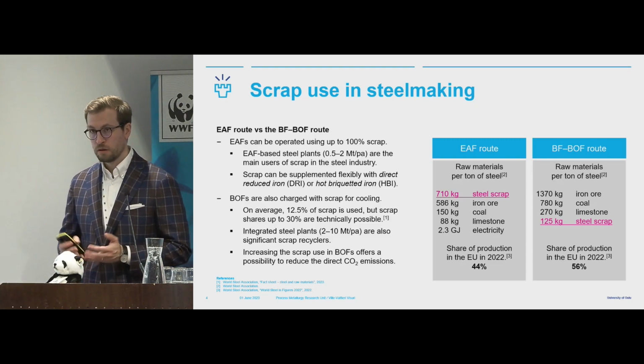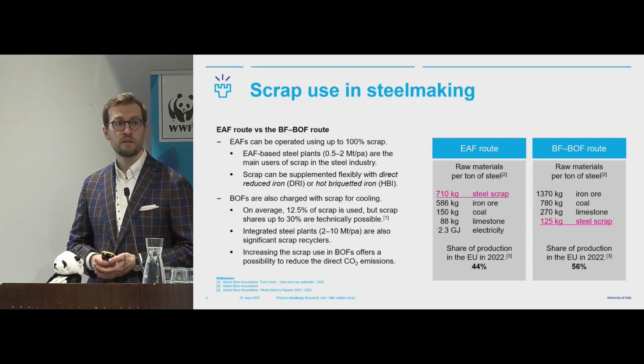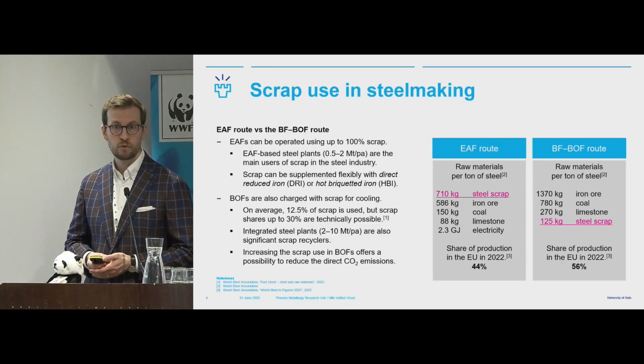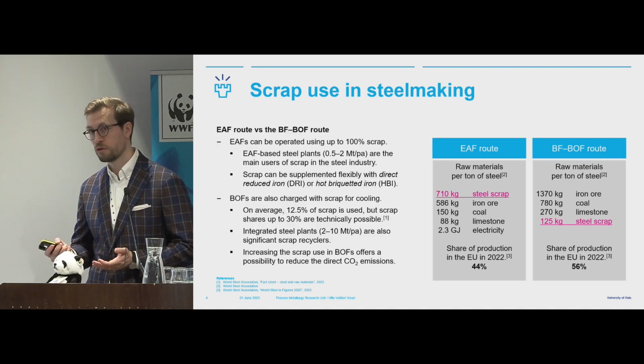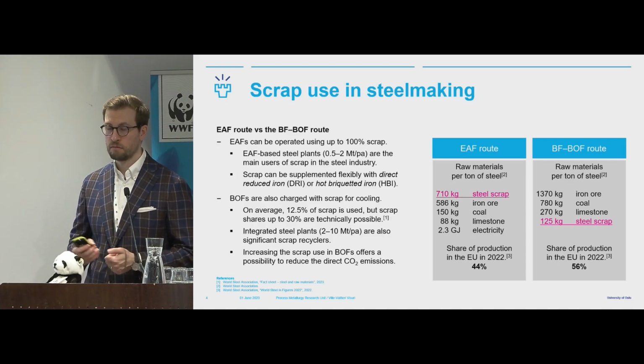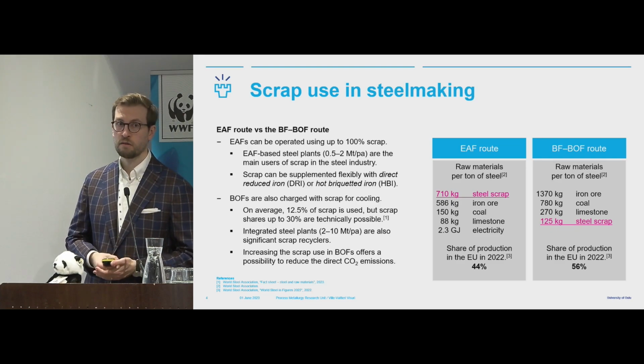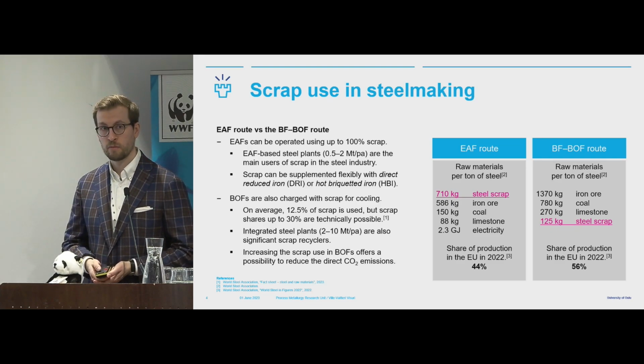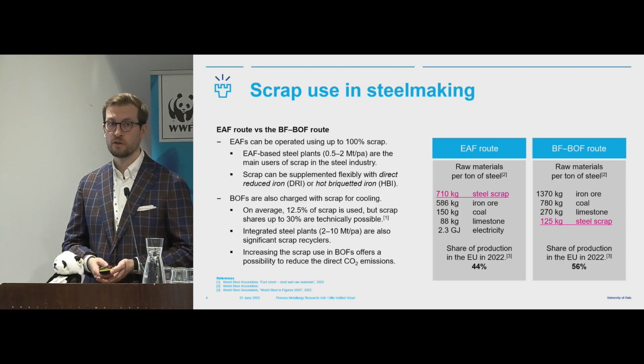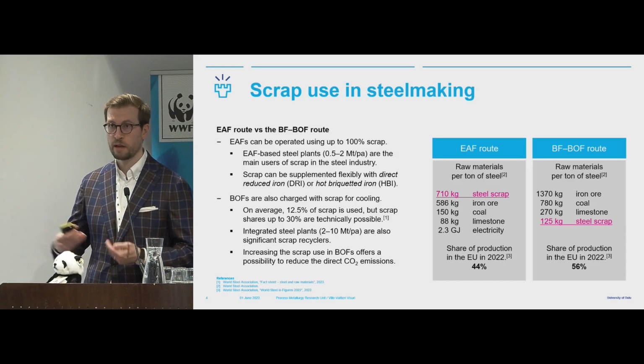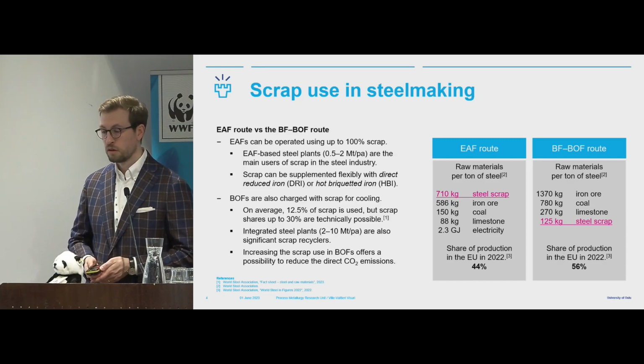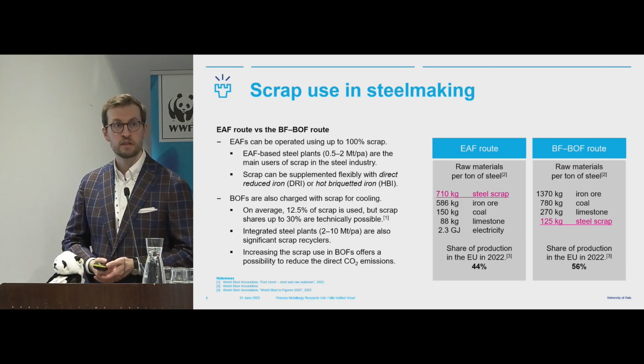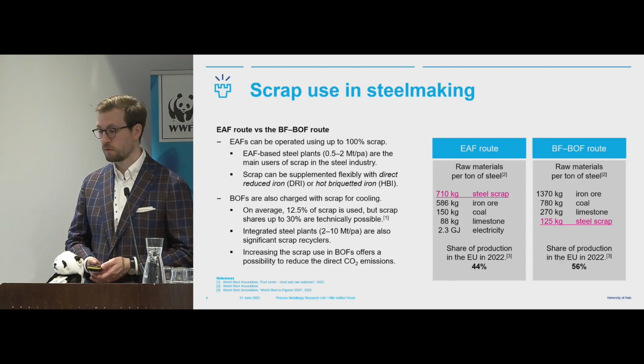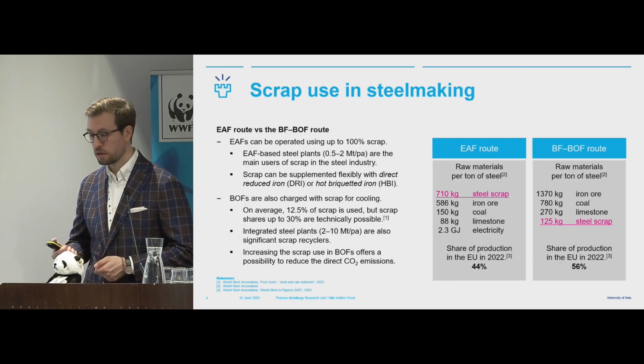The electric arc furnace process is very versatile in the sense that it can be operated with up to 100% scrap. We can also use DRI, or direct reduced iron, or hot briquetted iron to supplement it, and this is very common. The steel plants based on electric arc furnaces are typically much smaller than those plants which are based on the integrated route. So this means that although they're using very high scrap shares, the absolute amount of scrap is not as enormous as you would think based on this.